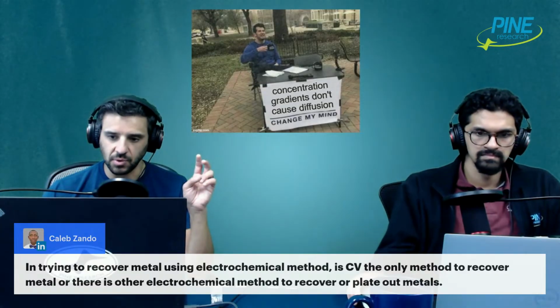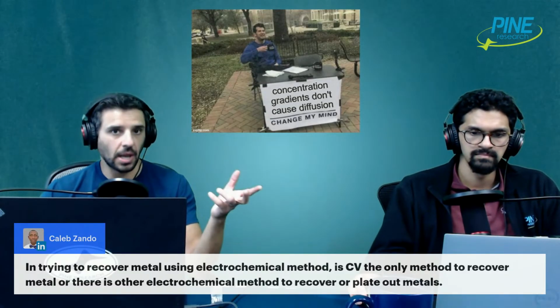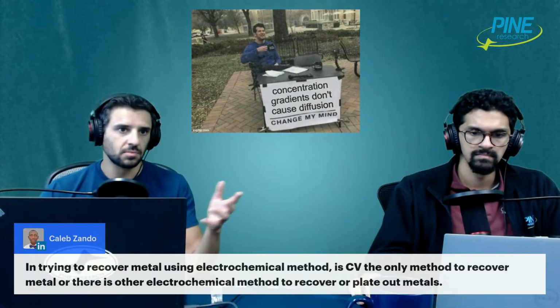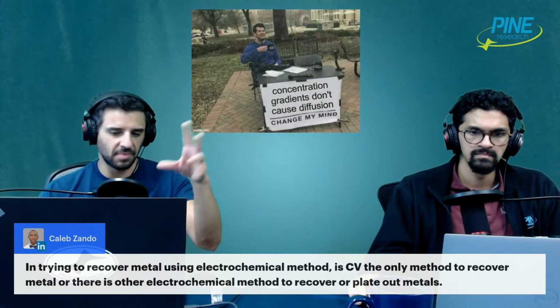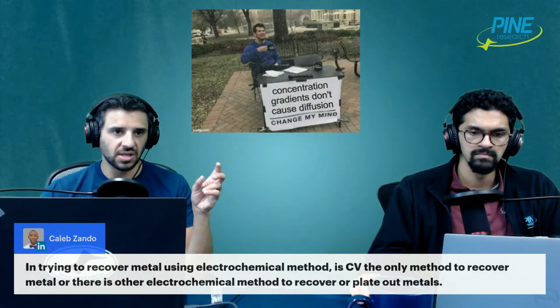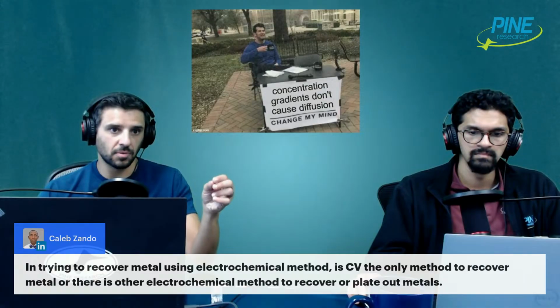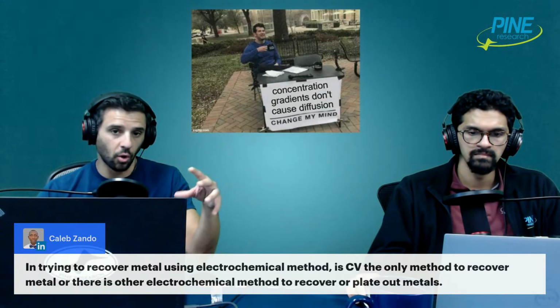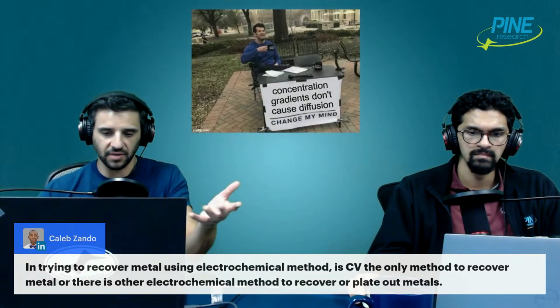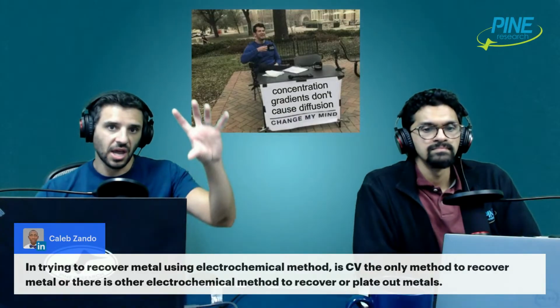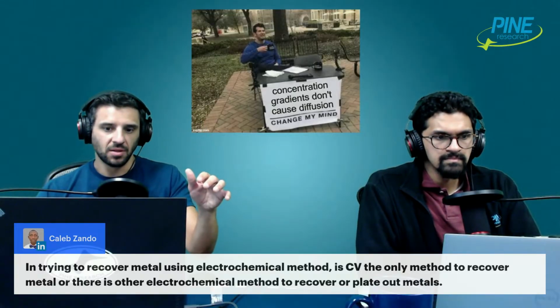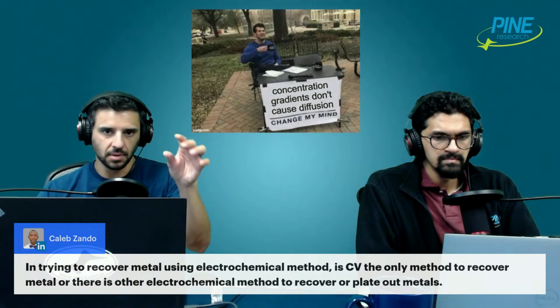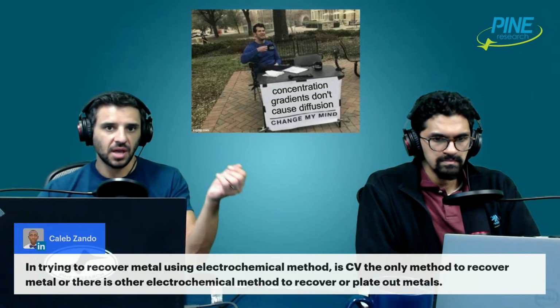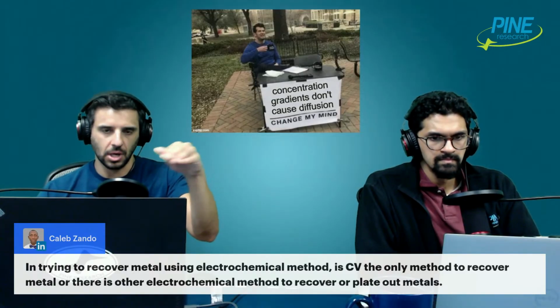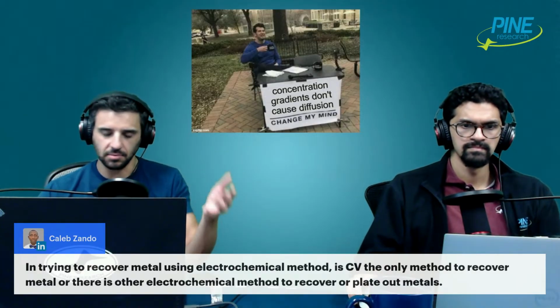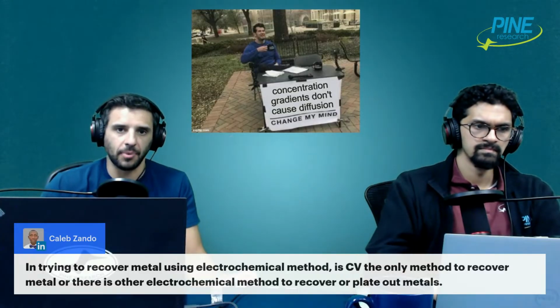Now, in a lot of cases, when you're recovering metal, what you're doing is an electrochemical process, as you've noted here, to reduce or oxidize it. So if a metal is part of some other mixture, you might be interested in oxidizing it to make it ions that float into solution, or the other way. And then you'll collect the solution and you have your ions of your metal. On the other hand, you could have ions in solution and you want to reduce those ions to make a plate. Like if you have copper ions in solution, you could put a platinum metal electrode into solution, put a reducing potential, and you'll get a film of copper to form. The copper ions will reduce to solid copper metal, and then you've recovered the copper from your solution.